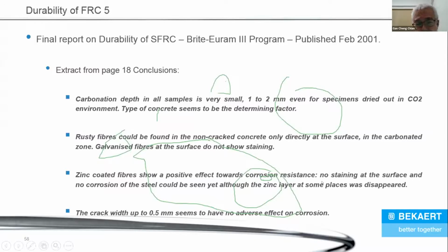Zinc-coated fibers show a positive effect towards corrosion resistance. No staining at the surface and no corrosion of the steel could be seen, although the zinc layer at some places has disappeared. The crack width up to 0.5 millimeter seems to have no adverse effect on corrosion. Now, for rebar concrete, we cannot allow 0.5 millimeter. But for fiber concrete, we can actually allow up to 0.5 millimeter and it still has no problems with corrosion. So this is the conclusion that was already published in 2001.